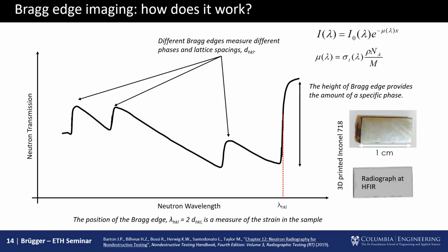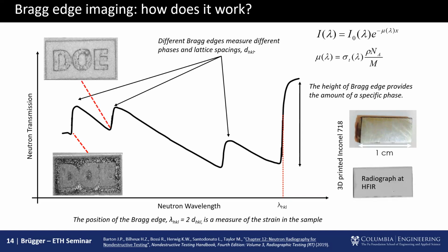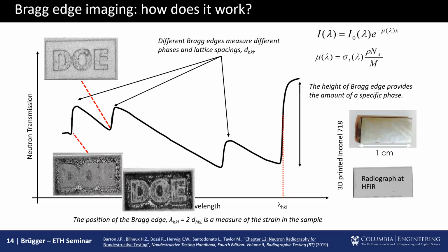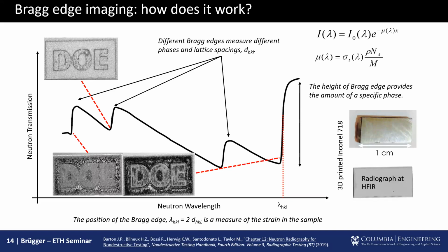It's the colorblind test. If you've ever seen the colorblind test and you're colorblind, you just see a gray mass. And if you see color, you see numbers, right? So this is exactly the same thing, because now here we can actually look at the disparity of the phases in parts of the print, and then suddenly, the word DOE shows up. So this is actually 3D printed with different phase content and phase fractions and strains in different parts of the print. So we're essentially looking at an optical manifestation of a disparity in phase content and strain in the material. So very cool, right? We're opening sort of a domain in imaging that we didn't have before.